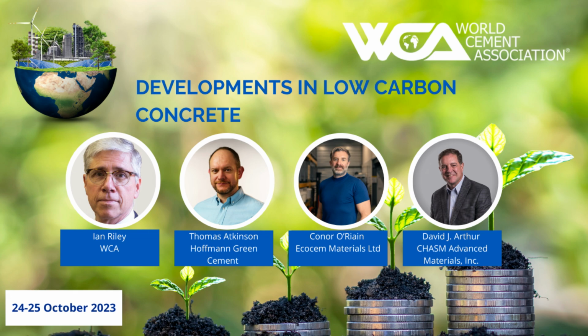How do we produce low carbon and low cost? Well, one way is, I heard yesterday a lot of talk about use of SCMs, and one of the limitations of SCMs is that sometimes it requires a trade-off in the early compression strength. The carbon nanotube materials are very, very high in surface area. In fact, they more than double the surface area of the cement material at a loading of only 0.1 weight percent. So when they're at the surface, they can improve the hydration kinetics, which can improve the early strength quite dramatically, about 30%.